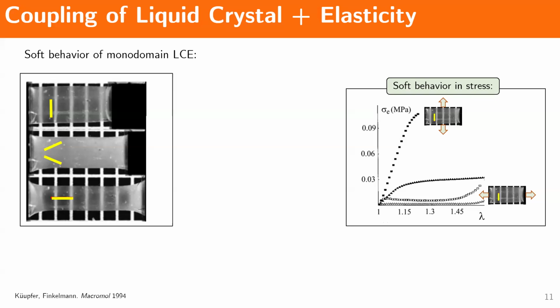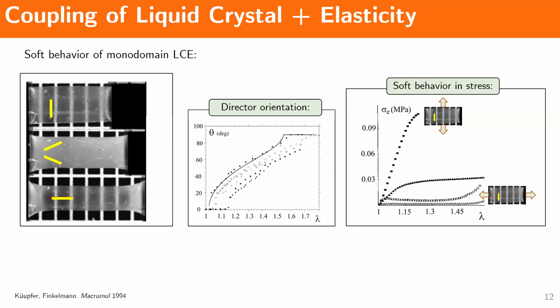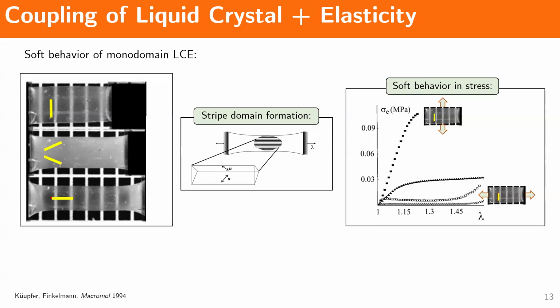And so here you see if you are loading a material in the direction parallel to your mesogen orientation, you'll get your regular stiff behavior that you would get when you're pulling on a rubber material. But when you're loading it perpendicular to your mesogen, for example, you'll get this soft behavior that happens when you have this plateau of stress under very, very large deformation. So people see this as well under X-ray, where they see this angle of director orientation changing with respect to stretch, right? So the underlying mechanism, however, behind this soft behavior is very, very interesting.